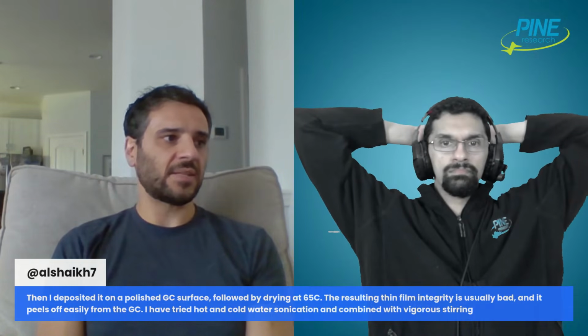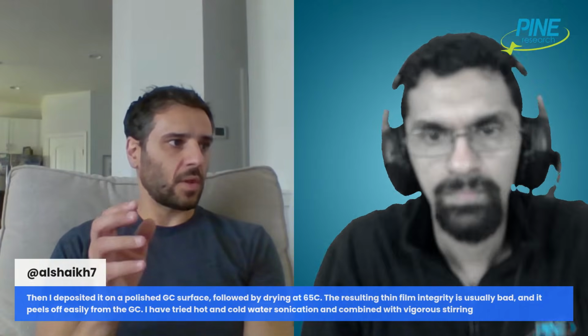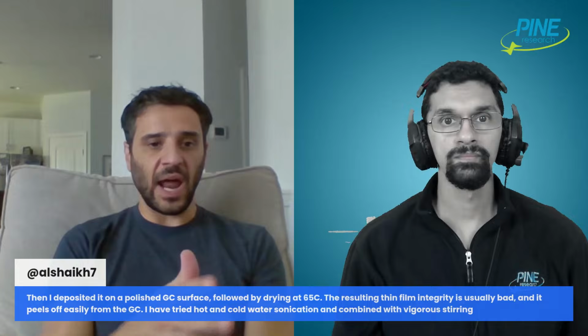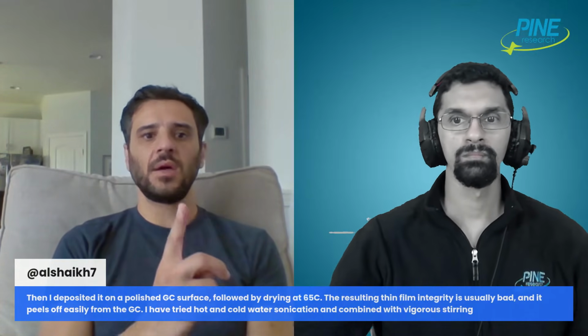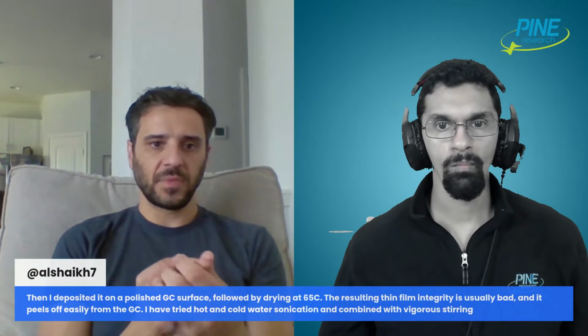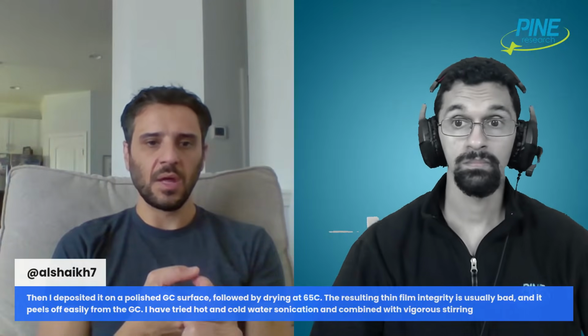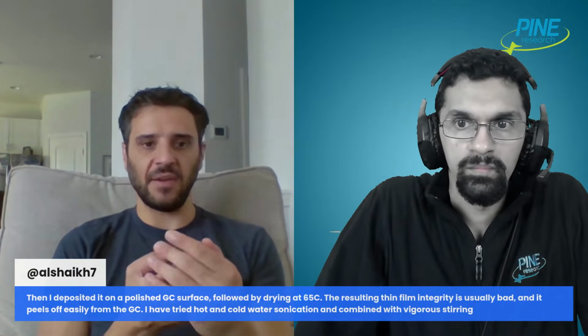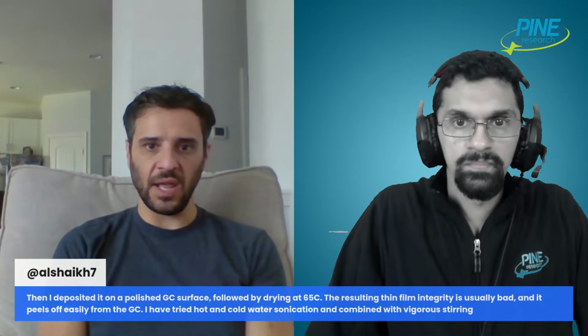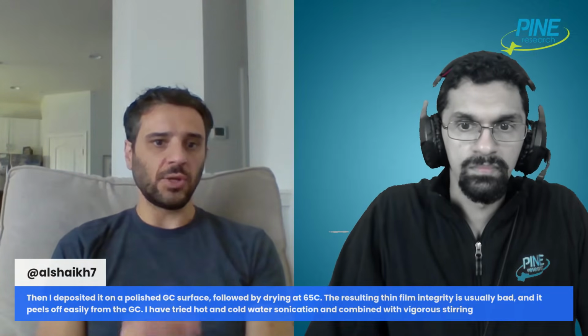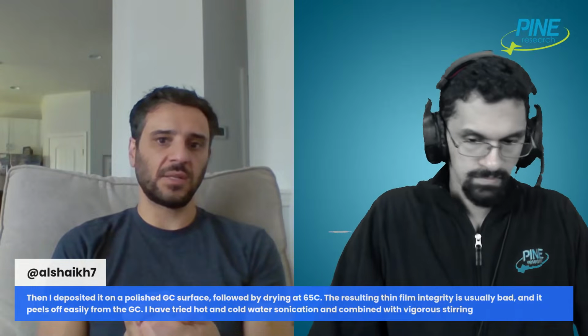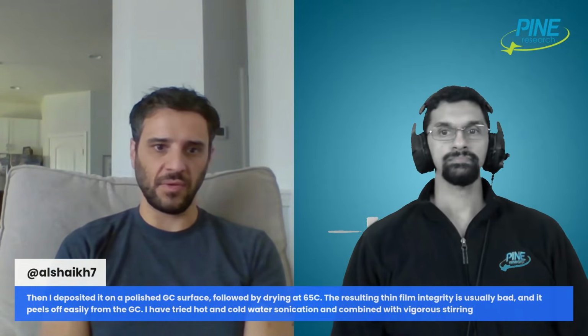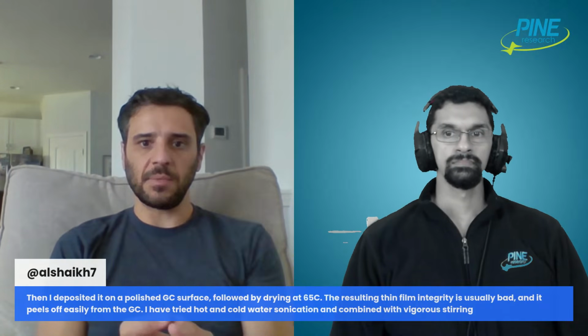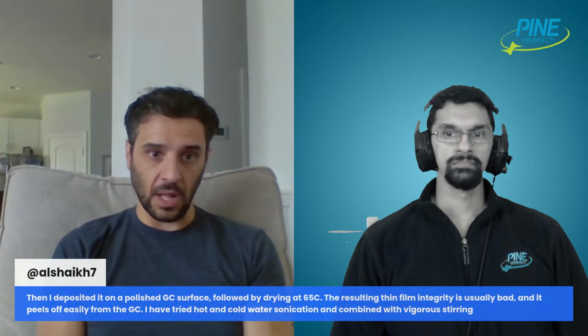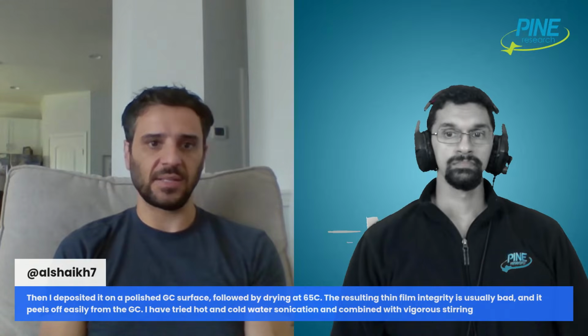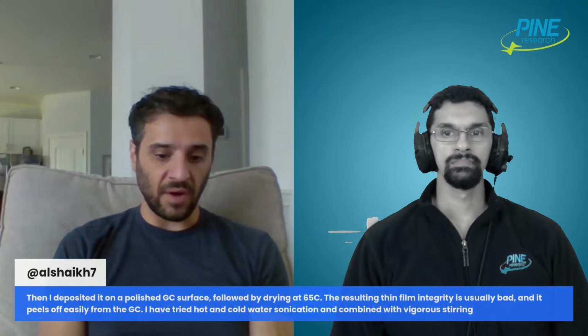Okay. The second is the procedure that you can try, that I used to use a lot more often. Instead of having one ink where I have, in your case, transition metal oxides, I use transition metal oxides as well, and then graphite for conductivity, and binder all in one in a solvent of ethanol or water or whatever, do 2 different inks. So one would be, in this case, a 7-to-2 ratio, maybe an 8-to-2 if you're adding up to 100%. Just make an ink consisting of your transition metal oxide and the graphite. So just the catalyst itself in whatever your solvent is.